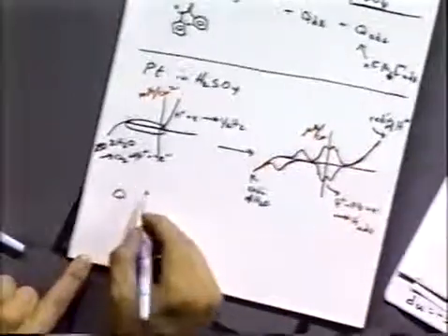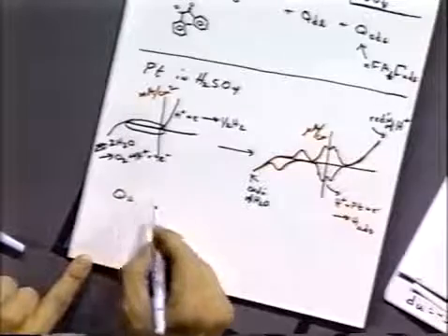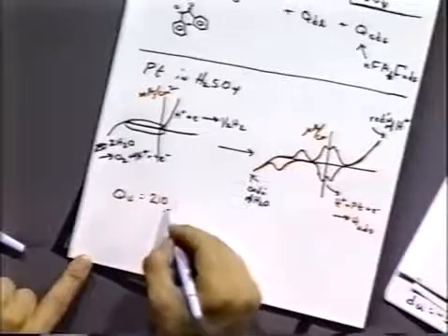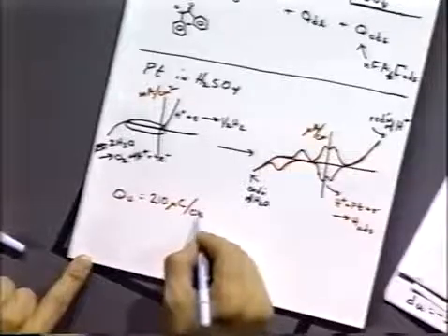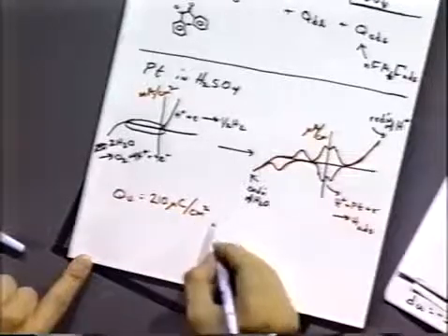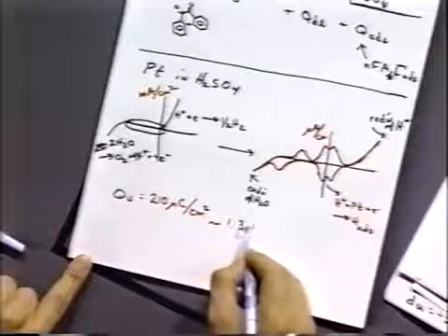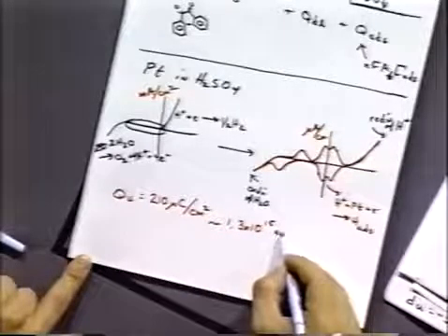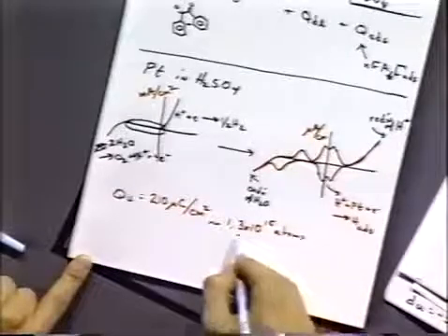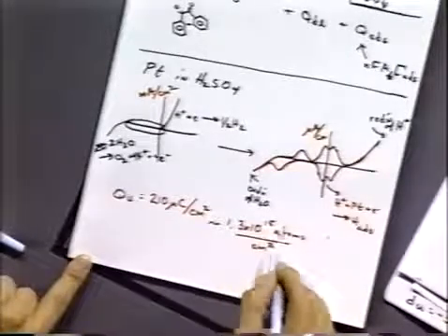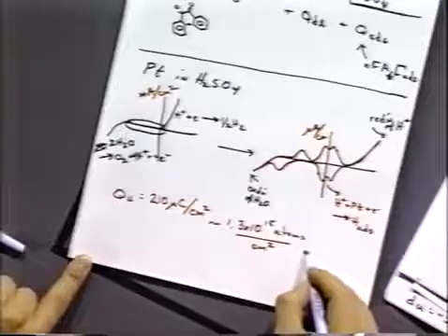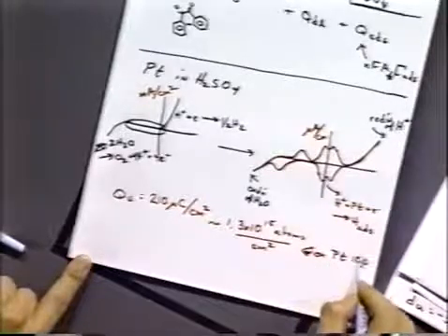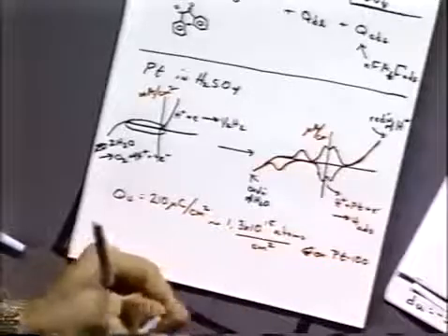So the charge associated with hydrogen is about 210 microcoulombs per square centimeter, or approximately 1.3 times 10 to the 15th atoms per square centimeter. And that's on a particular type of platinum surface of single crystal platinum 100 crystalline face of the platinum.